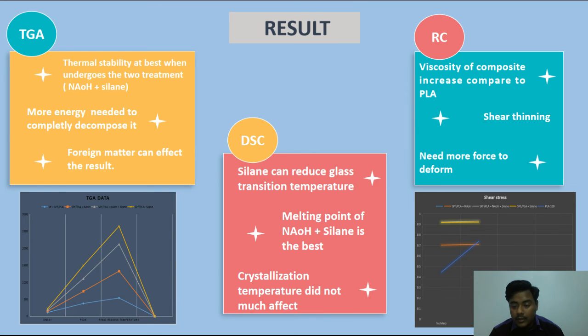What can be concluded from the analysis is that silane can reduce the glass transition temperature, and we also can see that the melting point of NaOH plus silane is the best, or the highest, among the treated fibers. The crystallization temperature did not have much effect, as we can see that the temperature is almost the same between all 4 samples.